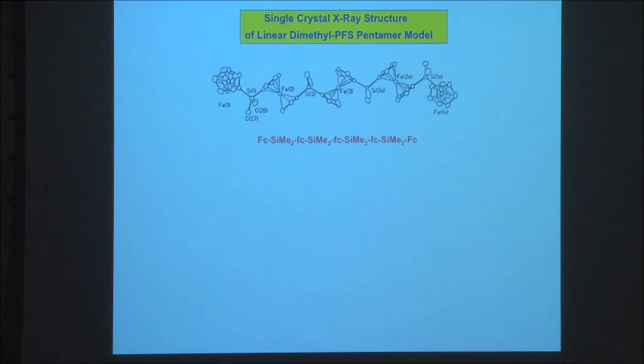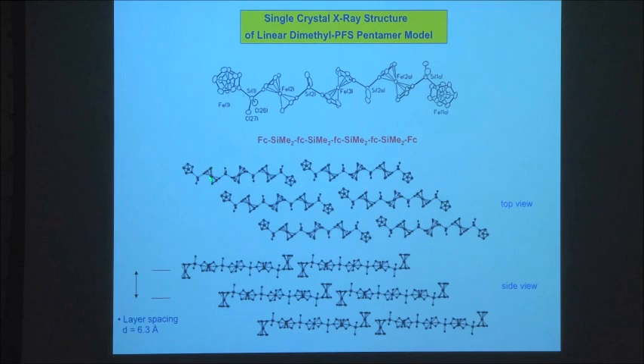And the molecular structure has this transplanar zigzag conformation. The ferrocenes at the end of the structure are out of the plane of the rest of the molecule. But you'd expect it's the middle bit of the structure that's the model for the high polymer, which of course has a very high molecular weight. And if you look at how these pack in the solid state, you see this transplanar zigzag conformation in these planes here. So this is a top view, here's from the side. And if you imagine removing these end groups here and just continuing in this transplanar zigzag conformation for this dimethyl PFS analog here, we feel this is how the analogous high polymer chains will pack in the solid state.